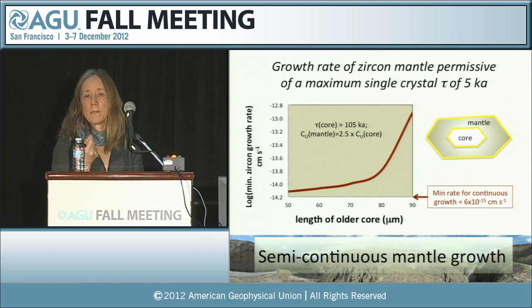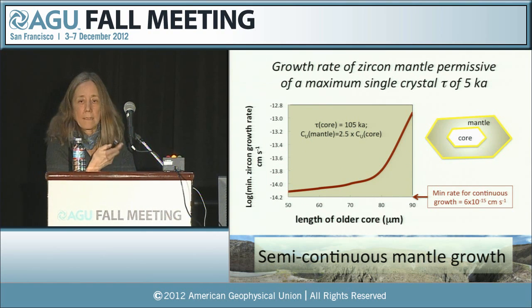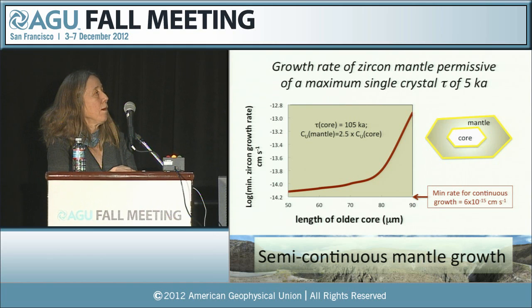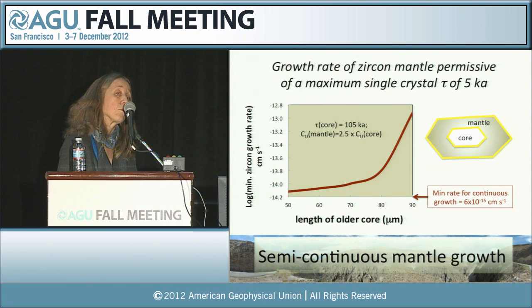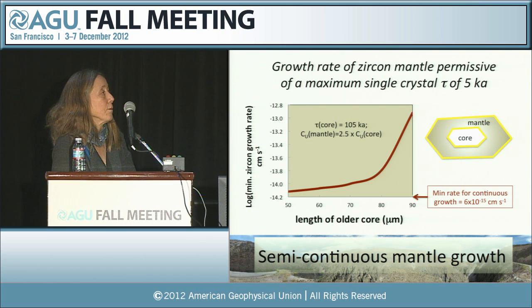It was probably unrealistic to assume that this mantling region grew instantaneously at the time of eruption. So I've turned that around and said, well, what could the growth rate of this mantling region be if we assume that we have a core of 105,000 years, and we superimpose on that a mantle that grows over some period of time? What would the growth rate be? And it works out this is what the trend looks like depending on the length of that older core. So in other words, what's the volume of that older core? And those crystallization rates turn out to be on the order of 10 to the minus 14 to 10 to the minus 13 centimeters per second. And those are quite reasonable estimates for zircon growth based on some recent work that's been done to try to constrain those things. So we still have more work that we can do in terms of mass balancing things, but